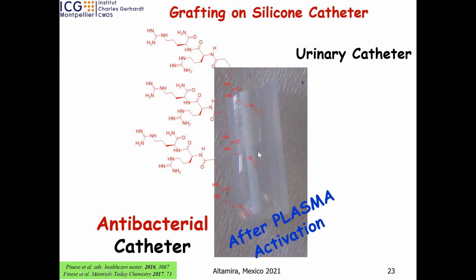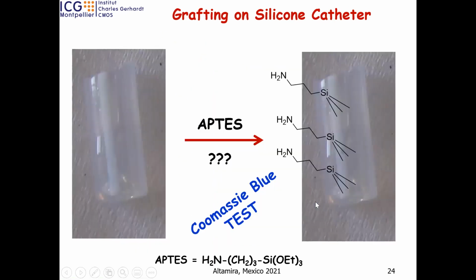I would like to show you briefly how we managed this work. First, we demonstrated that your surface should be activated by plasma. How did we find that? We started with just immobilization of an amino group on the surface, aminopropyltriethoxysilane, this one. So by hydrolysis, you can immobilize this group directly on the surface.